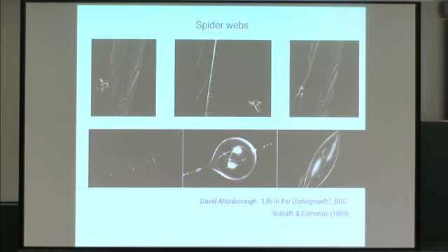They are a very gluey, very viscous liquid. Inside these droplets, you have an excess of length of the thread. And basically, when the fly deforms the web, the thread inside the droplet gets uncoiled. You deform a lot the droplet, and since it's a viscous liquid, you have viscous dissipation, and in the coiling back, it takes some time to coil back, and you have a damping effect, which prevents the fly from bouncing back. Very, very smart